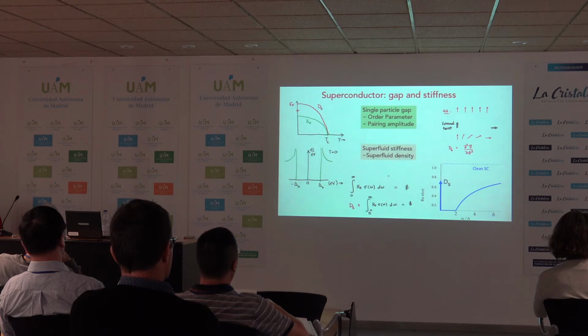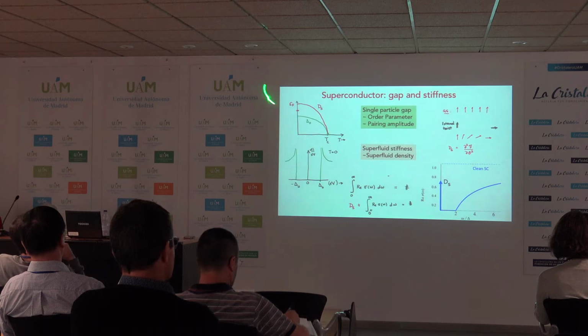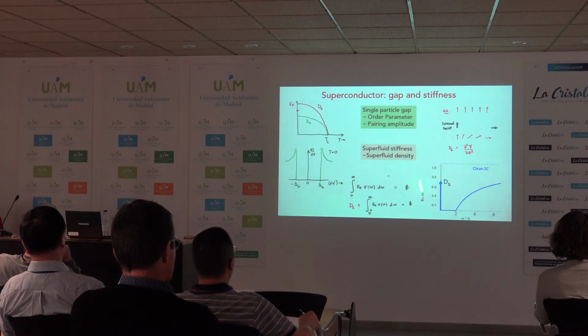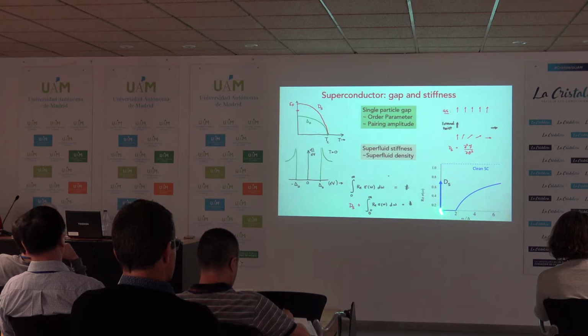But this is different from the way Seamus used the word. This is really a stiffness of the complex part of the superconducting order parameter. You can get the single particle gap from the density of states by looking at dI/dV. And you can get the superfluid stiffness either by doing a mutual inductance experiment and measuring the inductance, or from the absorption, the real part of sigma of omega versus omega. You don't get any absorption until you hit twice the single particle gap. And there's a sum rule which controls this absorption, so the total integrated weight is a fixed number.